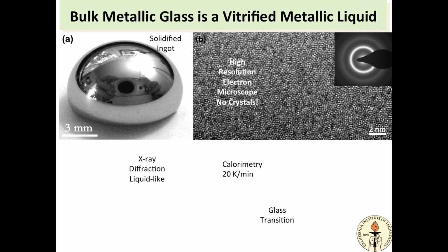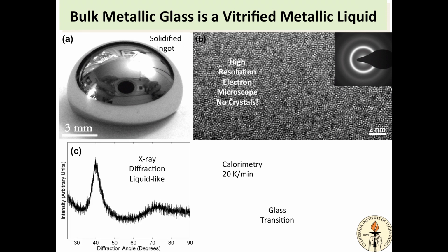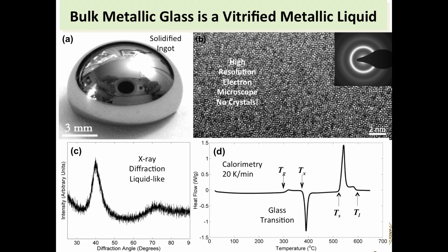the way we usually tell where the atoms are is we X-ray it, and the X-ray pattern looked like a liquid. It looks just like a liquid metal. And if you heat it up and look at how it behaves thermally, lo and behold, there's a glass transition. And you get up above the glass transition and it softens, like doing glass blowing on silicates. You go above the softening point, it gets soft, you can blow it, work it, so it softens up.